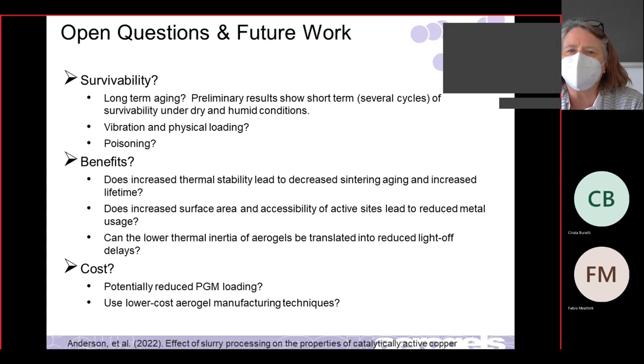Like we can test these in dry conditions, humid conditions. After it's been tested humid, we go back to dry, we see the same performance. But we haven't done thousands of cycles. We've done 5 cycles, something like that. How would they withstand vibration and physical loading? Poisoning is a problem, depending on what's in the gasoline. If there's sulfur in there, it can poison the copper and deactivate the catalyst. It's a problem with all of the catalysts.